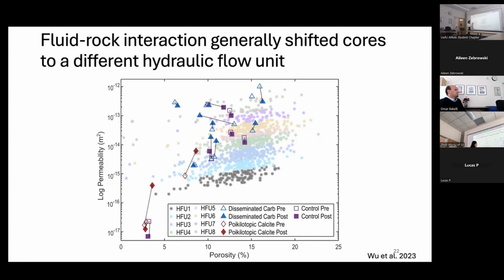So solid symbols are the post-measurements, and hollow symbols are the pre-measurements. Purple is the control experiment, so it means no CO2 was exposed to them. That's why the purple dots are really close to each other, because there's not much change in permeability and porosity. But the blue and the red data points tend to shift a lot compared to these background data points. They tend to jump from one hydraulic flow unit to another.